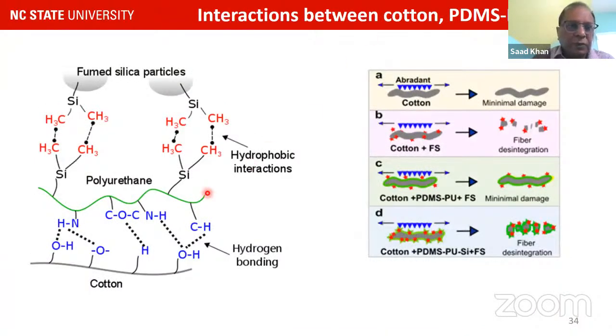What is happening? When we take a formulation and have a substrate, the urethane actually attaches to the cotton, and then we have these hydrophobics, the silica sticking out, which can interact with the fumed silica that we are putting in as a second coat. And so we have hydrophobic interactions and hydrogen bonding, and they're pretty robust in maintaining the coating. And we have seen that by doing aging tests and weathering tests and so forth.